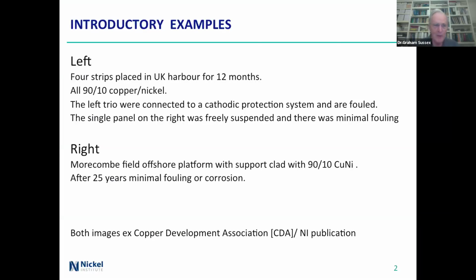The 4 strips there were in a UK harbour for 12 months. All of them were 90-10 copper nickel, and the left trio, the ones which had all sorts of stuff growing on them, were connected to a cathodic protection system so that they would be protected. But of course, they were all copper nickel, so they didn't need it. What that did was it stopped the copper from dissolving, which stopped the copper from preventing things from growing on them, and bingo, so they fouled up.